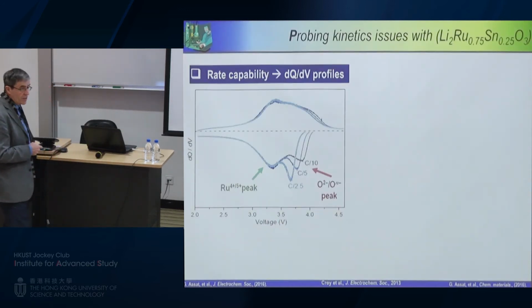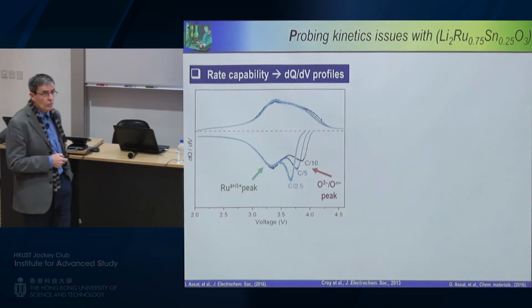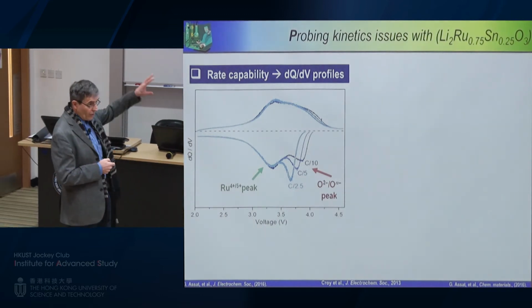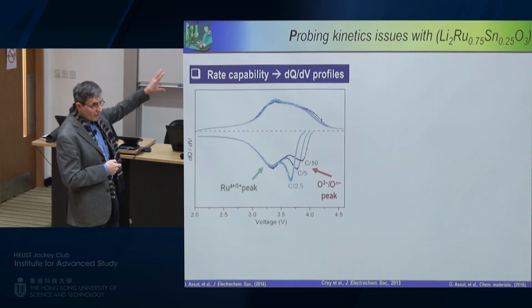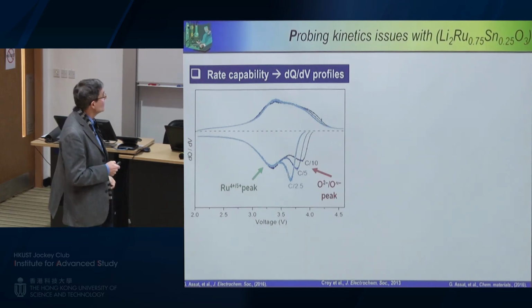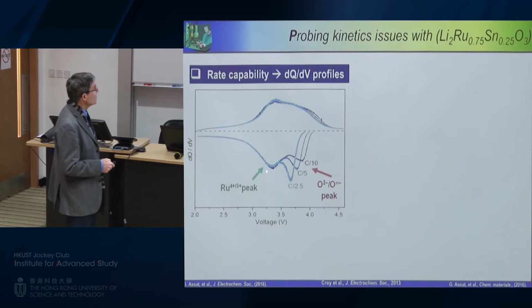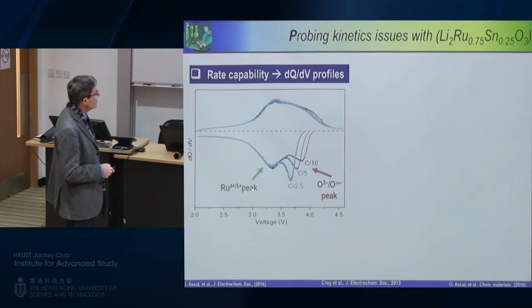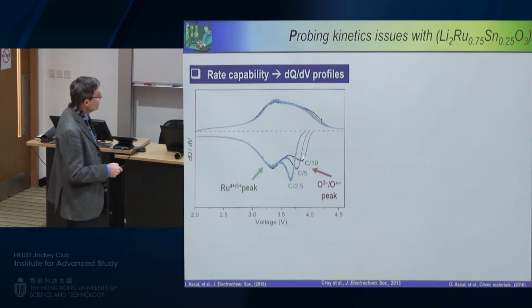Then, if I turn to the kinetics, here we are going to see the issue. And I think this is a very important issue for model materials, but also for lithium-rich NMC. Indeed, what you are looking at here is a cyclic voltammetry curve, where you can see nicely the peak associated to the cationic and the peak associated to the anionic. Look here, at C over 10, you have the black curve.